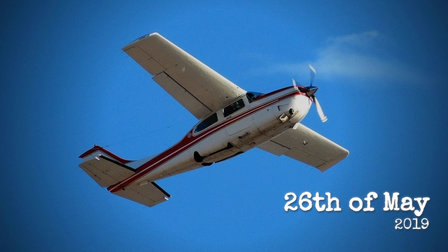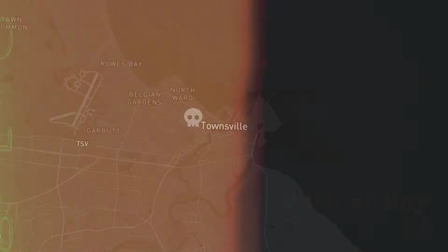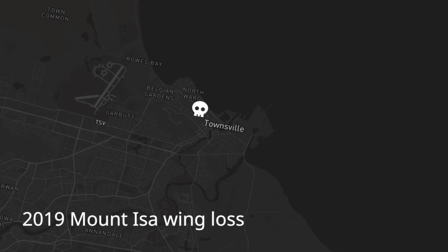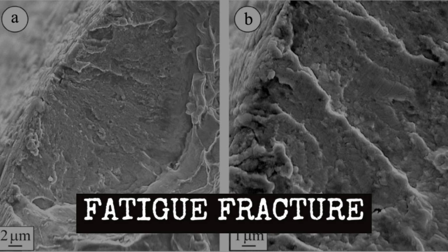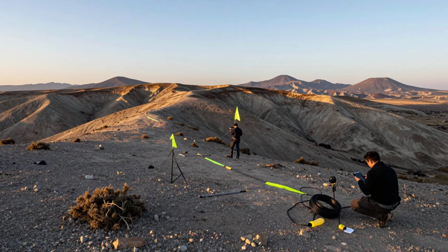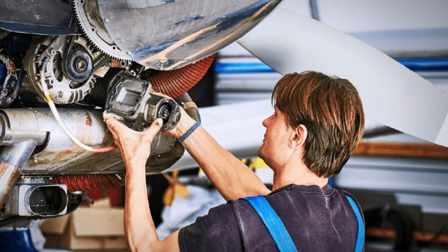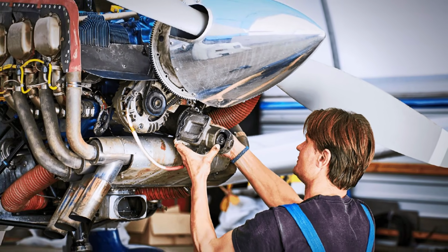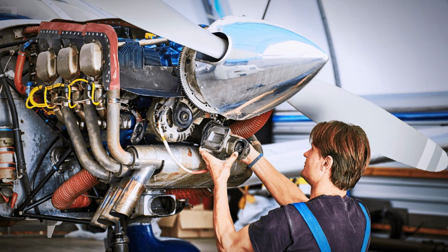On May 26, 2019, a Cessna T210M conducting low-level geophysical survey work near Mount Isa, Queensland, Australia, lost its right wing in flight. Both occupants died. The Australian Transport Safety Bureau found a fatigue fracture that had grown from a corrosion pit on the lower spar surface, exactly where the 2011 inspection downgrade had removed mandatory eddy current examination 8 years earlier.